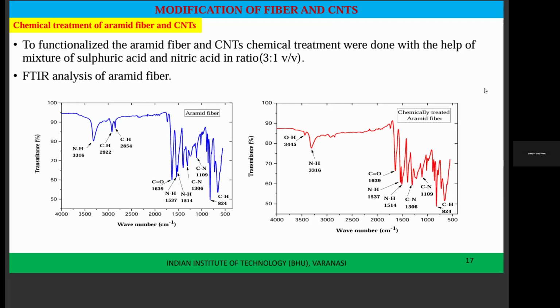We can perform FTIR analysis taking a small strip of the coated aramid fiber. You can take a small strip, and before coating the aramid fiber also you can take a strip, and perform this FTIR analysis. From that, you are going to see transmittance as a function of wave number. In the first image, certain groups are there, and this is the uncoated one. The second one is the chemically treated one. The only difference is there is an OH at 3445 wave number. It is formed from the chemically treated hydroxyl group.